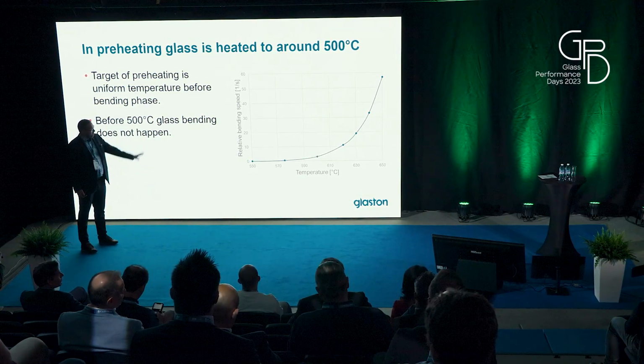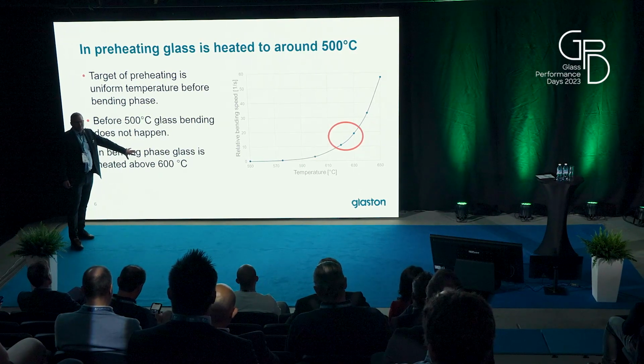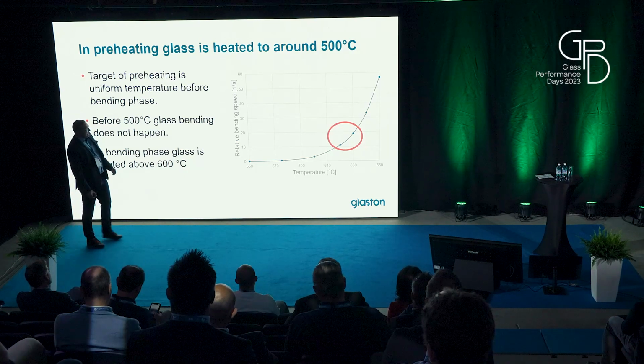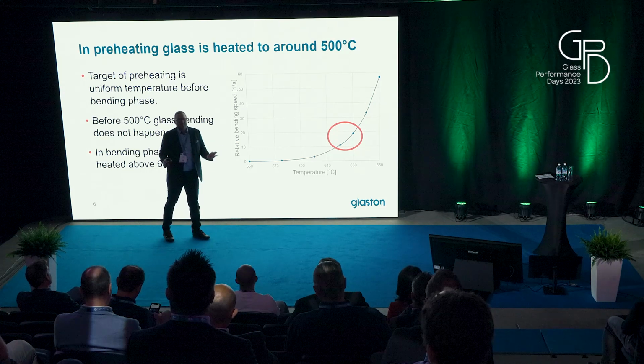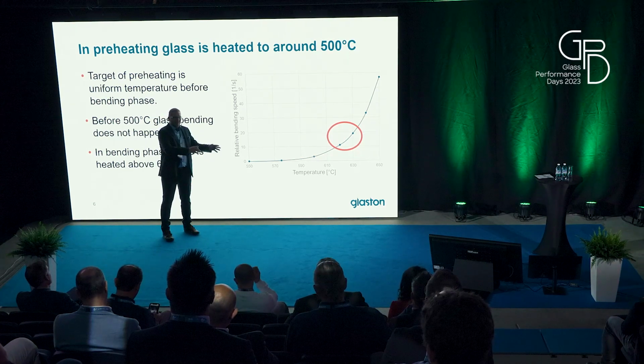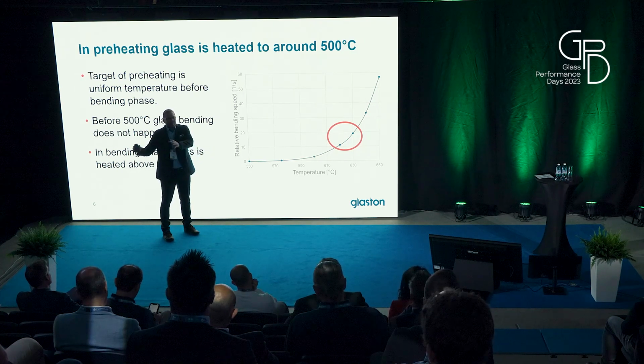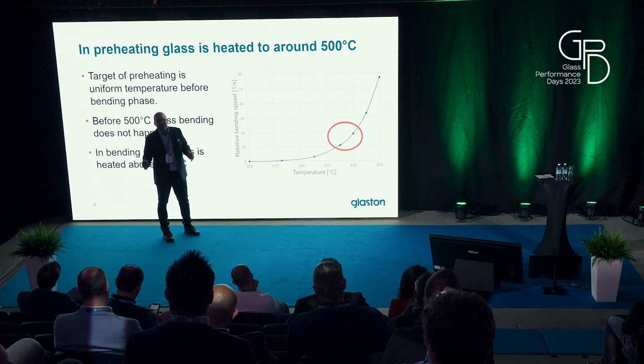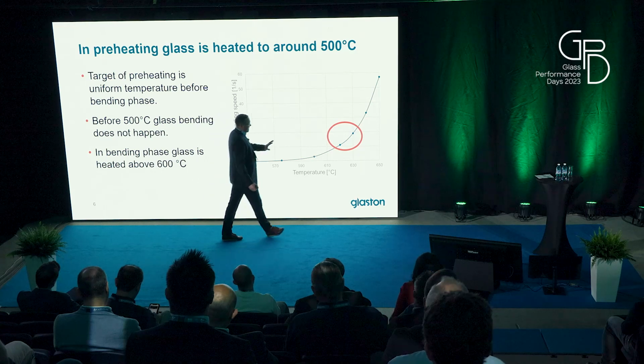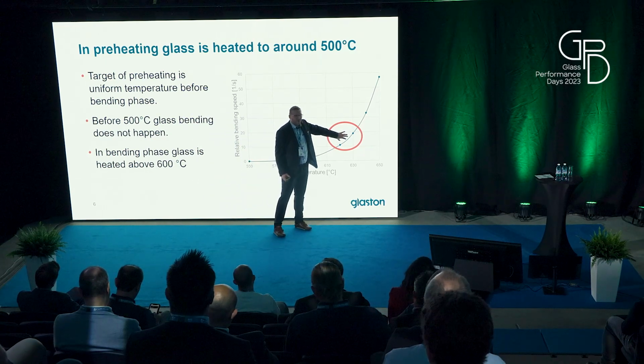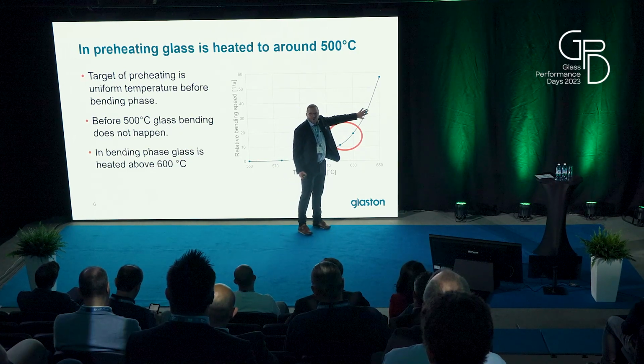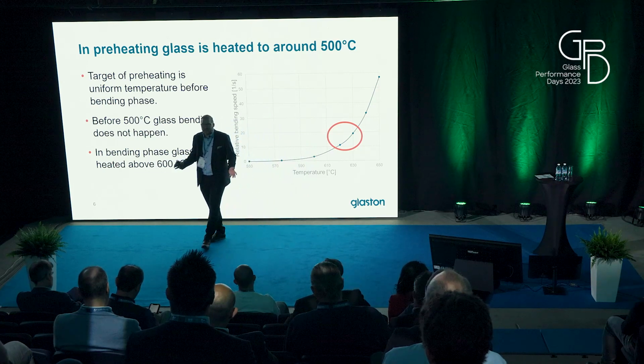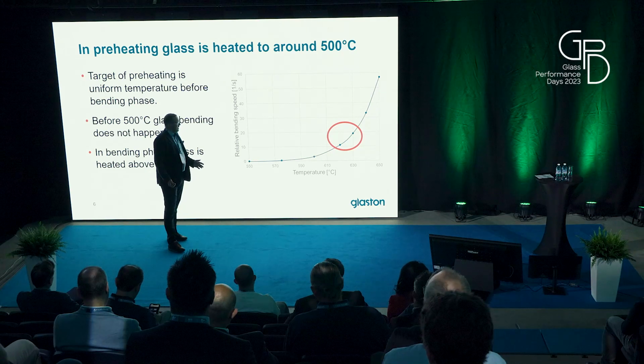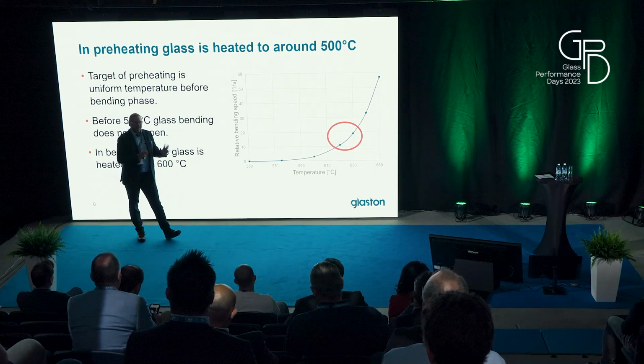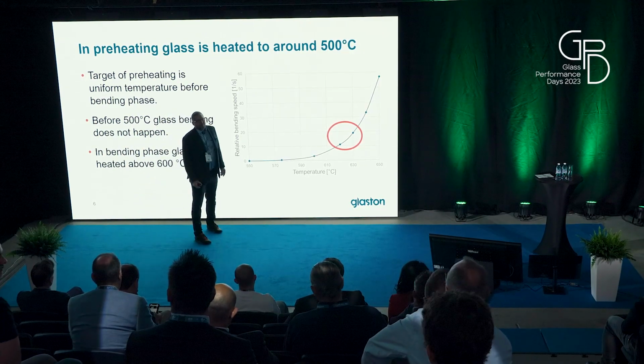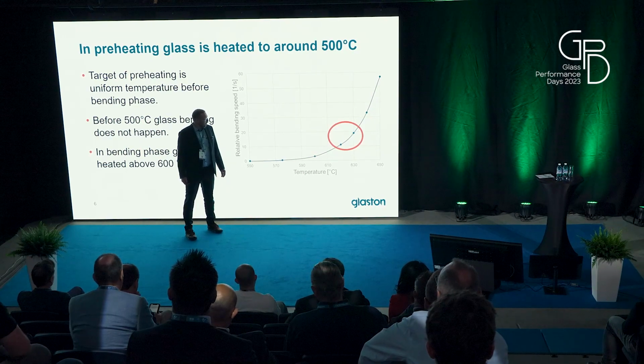But when we go further into the bending part, the glass temperature is 620 degrees, 630 degrees. And if in the preheating part you get some places in the glass where in one area there is a 500 degree area, and another place is at 550 degrees already, and then you go to the bending part, it can be that your target is to get glass to around 620 degrees, but at the end, some parts are going up to 640, 650 degrees, and that makes problems in your process. So that's why the preheating part is important, so that it makes the bending part easier to solve.